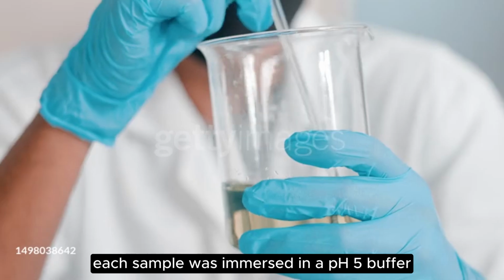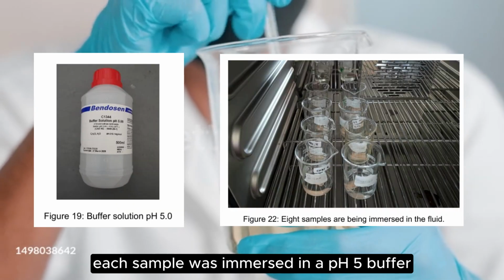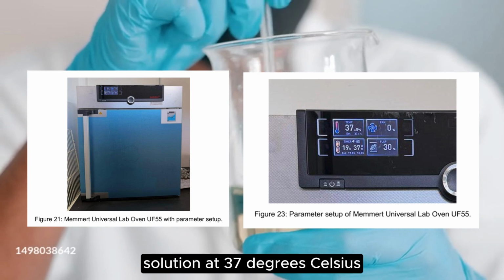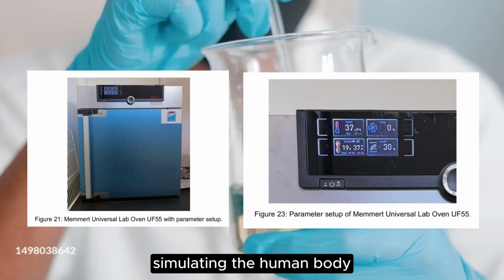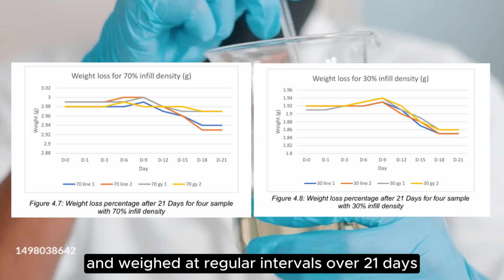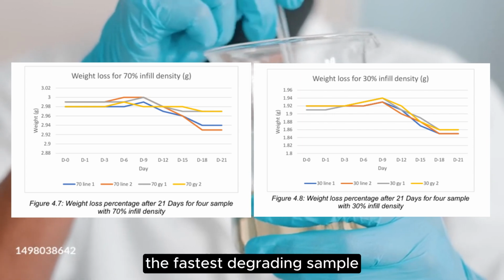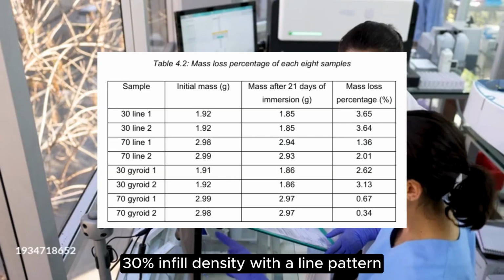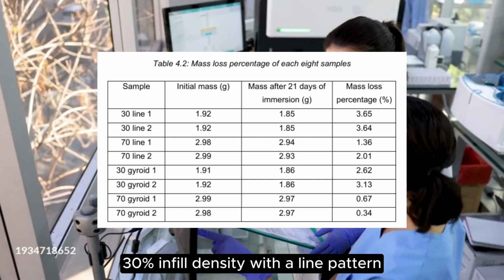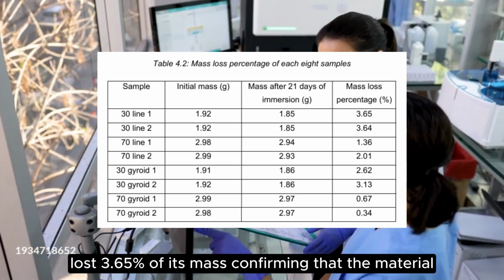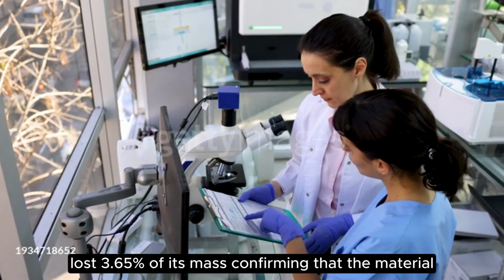Second, we evaluated degradation. Each sample was immersed in a pH 5 buffer solution at 37 degrees Celsius, simulating the human body, and weighed at regular intervals over 21 days. The fastest degrading sample, 30% infill density with a line pattern, lost 3.65% of its mass, confirming that the material